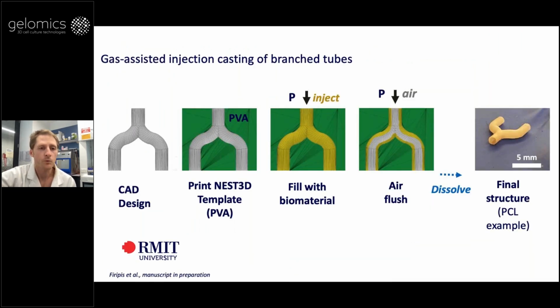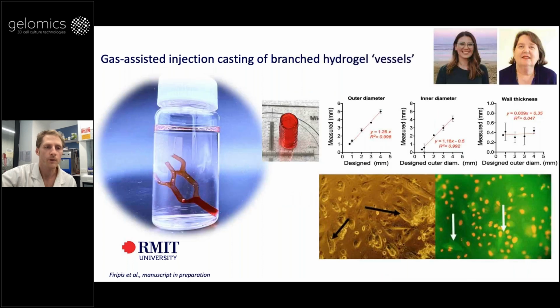And one final innovation is you can use a process called gas-assisted injection molding, where you fill up your mold, then blast out the insides, and then you get hollow tubes, hollow branched tubes, which we've developed into a hydrogel branched vasculature for seeding with endothelial cells. We can control the thickness of the walls.